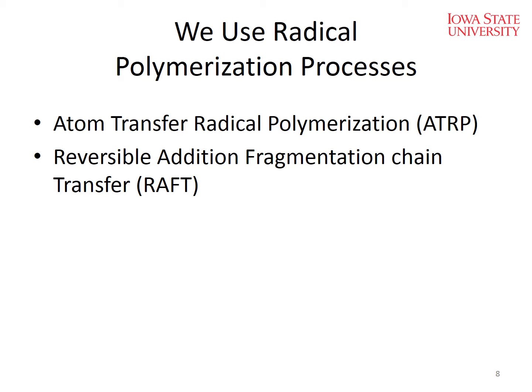Now, in RAFT, we have an option of building our polymer chain on the end, but we've also developed a system where it's like a gearbox. And so as these gears are spinning in the middle, we can actually grow the chains from the middle with a gearbox kind of system. Gears turning out, the polymers in the middle. And we can control the molecular weight and the chain of these polymers very, very well. So our preferred process right now is the RAFT, actually. Okay.